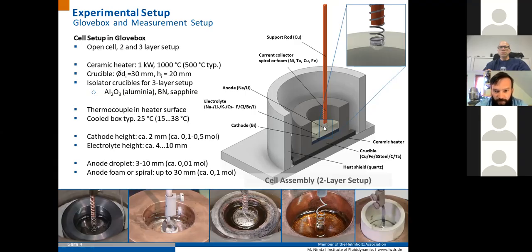The anode droplet, this lithium droplet here, is usually of a diameter from 3 millimeters to 10 millimeters. You can see when using spirals or foam electrodes or current collectors, the electrode itself could be quite large. And there we can use up to 30 millimeter diameter electrodes, which then contain roughly 0.1 mole lithium.